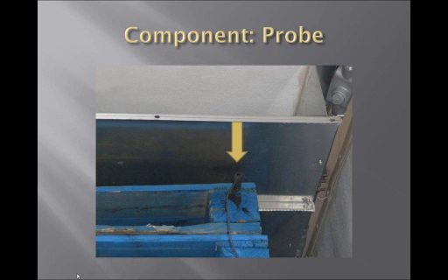Core probes, which we'll talk about as well, are, as you can see from this picture, plugged directly into the thickest part of the wood, and they monitor the internal temperature of the wood or of the pallet. They typically use the thickest piece of lumber within your chamber. In the U.S., 3 of these probes are used to monitor the charge, while in Canada we use 1, which will signify the start of the charge.